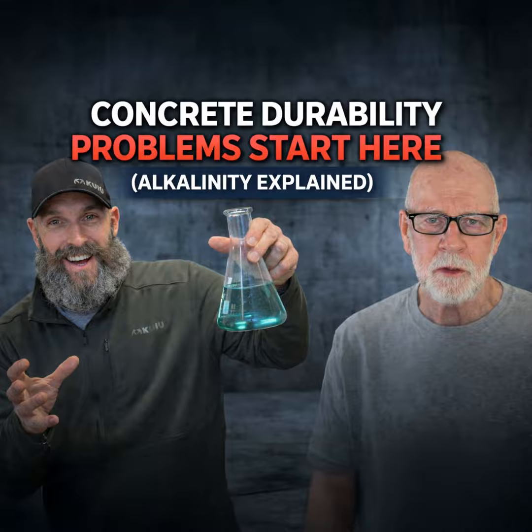It's not available for the cement. The kiln dust that's causing the high alkalinity, that was because of the EPA restrictions. Correct. Right. That was a requirement. So it's not releasing that dust anymore, and that's dropping down into the cement. Is that right? Do I have that right? Basically, with the more alkaline cement, it gets to that point very quickly. The cement hydration isn't as complete as it used to be.